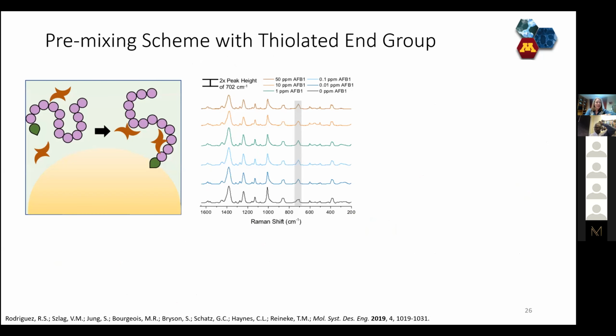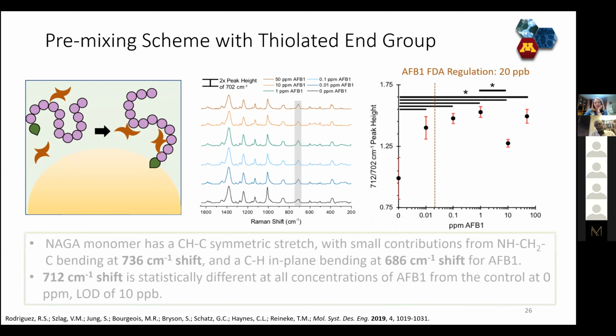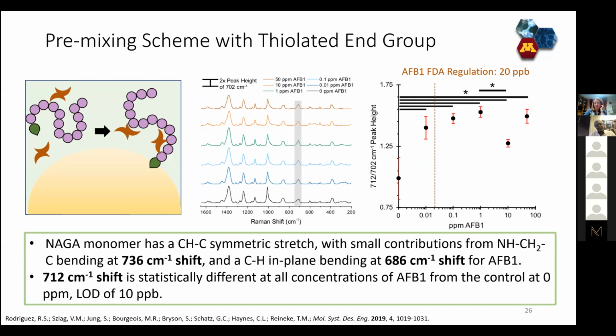So thiol terminated 22-mer of NAGA interacts with aflatoxin, then we put it on the surface. The black spectrum is the negative control again, so there's no aflatoxin there, and you have increasing amounts of aflatoxin as you go up. And we do see a nice new peak that definitely is attributable to our aflatoxin. And when we go through and actually quantify how big that peak is compared to a control, now we are doing much better. We have a limit of detection of 10 parts per billion. So we were actually able to get below that 20 parts per billion limit, which was really exciting. It told us that we had something that might actually be potentially useful.